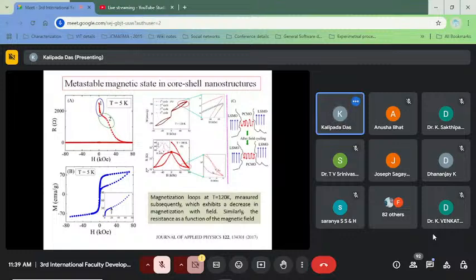Similarly, magnetic field versus magnetization showed an open hysteresis loop due to the charge ordering melting. And if we zoom in here, we see a common phenomenon known as the magnetic training effect in phase separated compounds. The magnetic training effect is nothing but that, due to the magnetic field cycling repeatedly, the magnetic ground state becomes more stable. That is, the metastable state tries to go to the stable one. Here, the antiferromagnetic spin configuration is enhanced slightly due to the field cycling, which is a very common phenomenon for phase separated compounds, and this phenomenon is still present here.